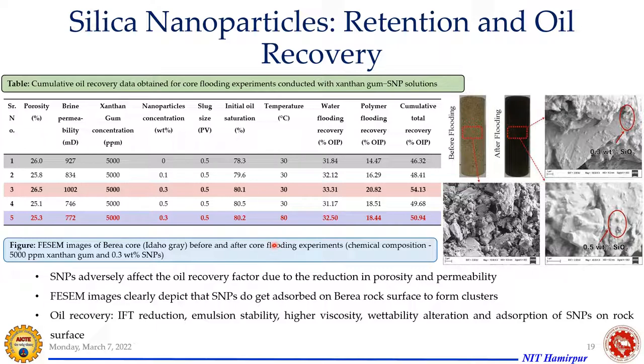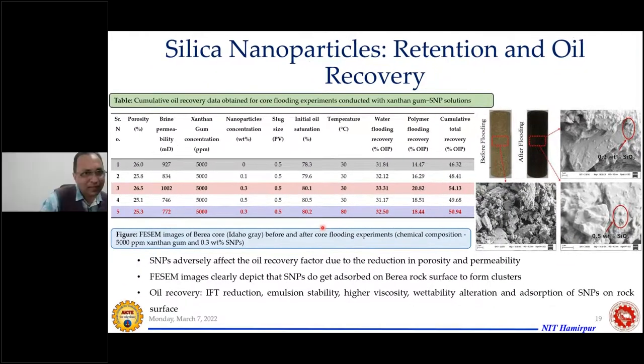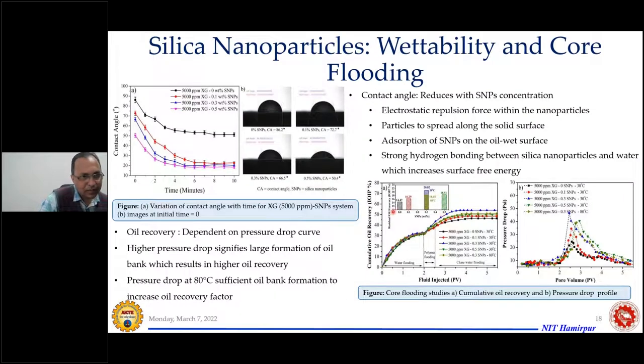Next is, so this is a very simple experiment where we have taken this polymer and we have just seen how the nanofluid in presence of polymer and in absence of polymer behaves and how the oil recovery is being altered. You can easily identify from this data itself. You can see, okay, when you were not having any chemical, the recovery was 14.5, and with chemical it reaches around 21%. So you can see around 6% oil recovery is enhanced by the use of this nanoparticle.